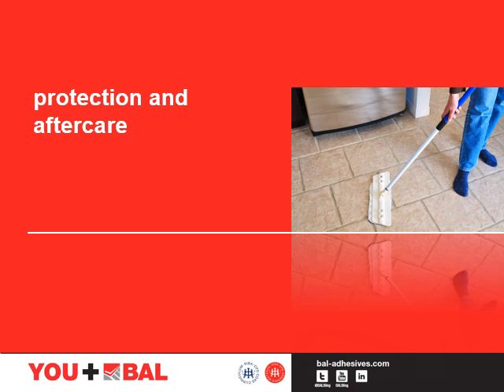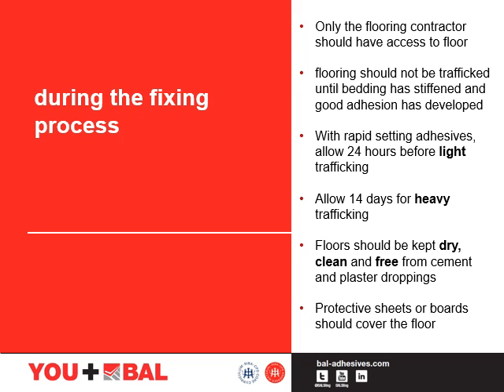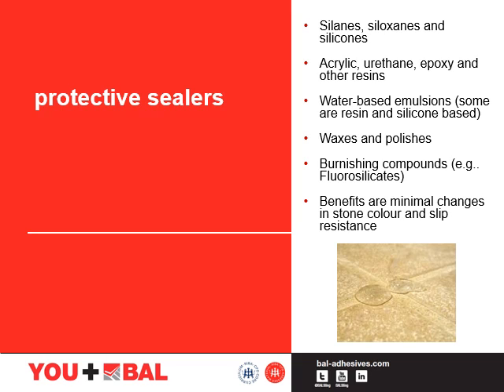As we went through the associated problems with natural stone installation, we know that natural stone is prone to the risk of staining. Therefore, protection and aftercare should be considered when fixing natural stone. A few watch points: the flooring contractor should be the only one to have access to that floor. Rapid setting adhesives allow 24 hours before light foot traffic and 14 days for heavy foot traffic. The floor should be kept dry and clean and free from any kind of droppings, be it cement or plaster. Protect with sheets or boards to cover the floor and ensure a good finish. There are various types of sealants or protective sealers available for natural stone. Different stones may require different treatments and some treatments will only be effective against certain types of stain. Seek further advice from a stone producer, manufacturer of a proprietary sealer, or contact the Stone Federation of Great Britain.